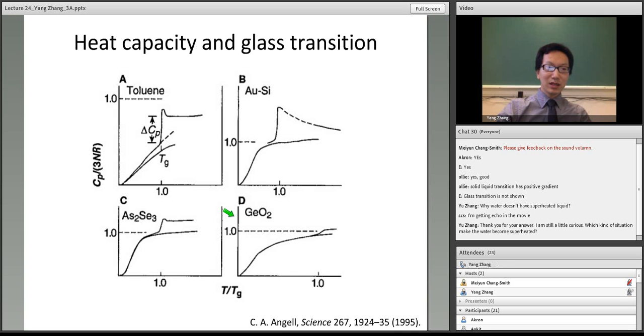As you can see, when we measure the specific heat capacity of a material as a function of temperature, let's look at figure A. When the temperature is lowered, if crystallization is avoided, we can still have a change of the heat capacity around Tg. So the glass transition is actually defined at the inflection point of the specific heat. We can measure specific heat with something like differential scanning calorimetry or some other instruments. Okay, a lot of them seem to show universal behavior. The specific heat shows a significant change, but it is still a continuous change.